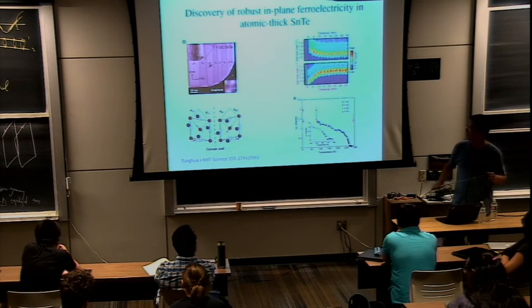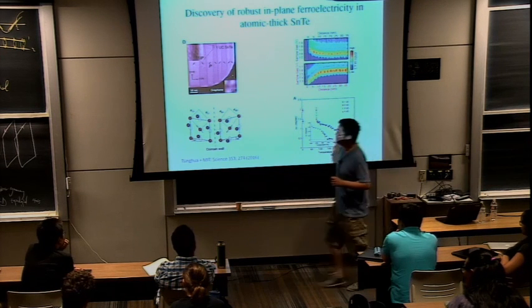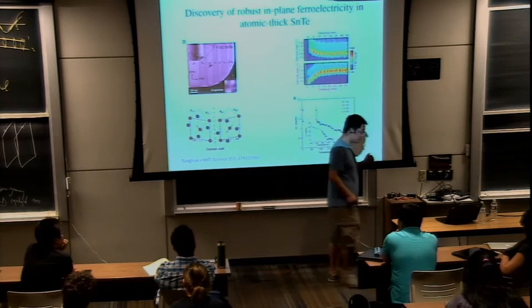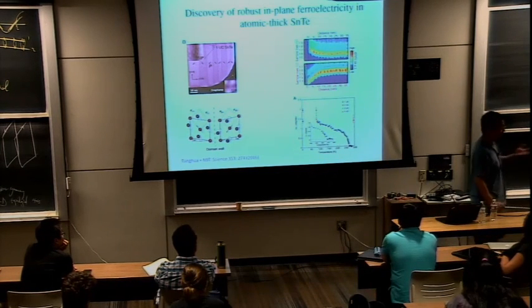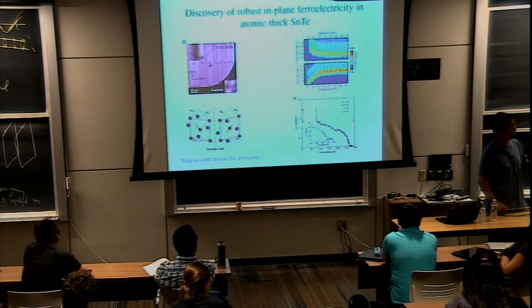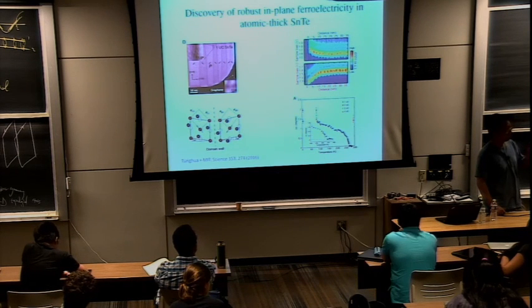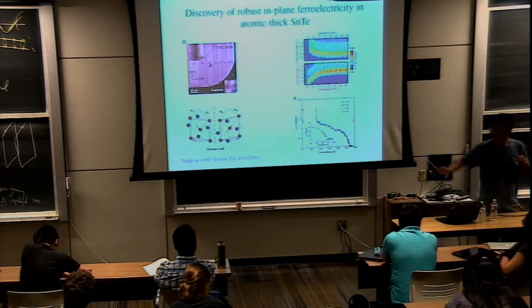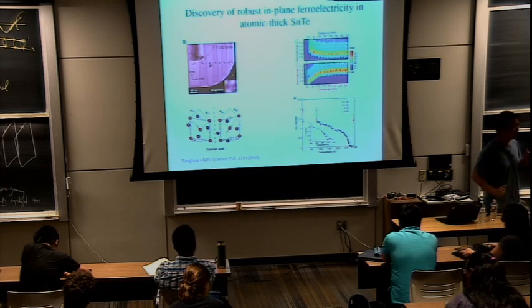So what happens is that if you take, for example, n equal 1, then you have just a single Dirac cone, very similar to a topological insulator in that case. Then you can make an alternating domain wall. But in the domain wall, you only have chiral fermions instead of helical fermions. So the minimum is n equal 2, with two Dirac cones, as I showed, if I have Dirac points at k and minus k. That corresponds to mirror Chern number 2. Then if I make the domain wall, there's a helical fermion with one left mover and one right mover. So that's why there's a factor of 2.